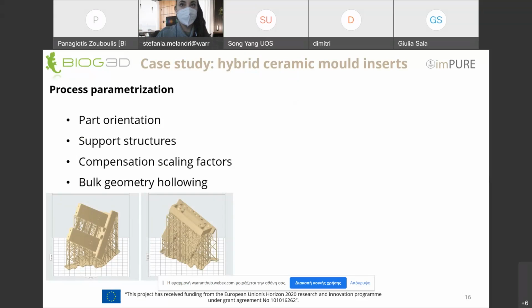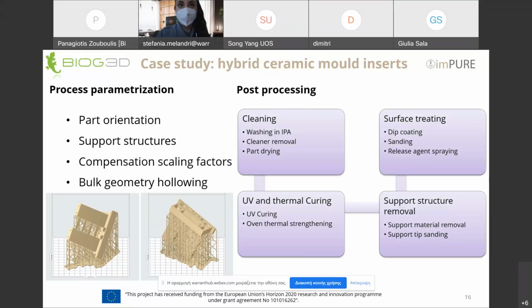Also, some bulk geometry requires hollowing in order to prevent distortions and warping during the post-processing of the part, always with consideration to retain the mechanical integrity. After printing, we have a thorough post-processing protocol that must be adhered to. We have cleaning using a solvent to remove residue of uncured resin, and UV and thermal curing in order for the part to achieve its final